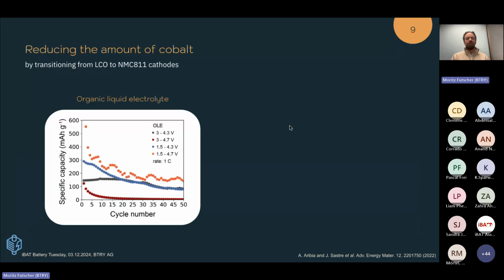So let's look first at the NMC811 cathode. This is work which was developed by Abdesselem Mahmoud Bia, one of the co-founders of the company, now the CTO, who developed processes for NMC811 as a cathode. And as far as I know, we are still the only ones who can fabricate these materials and these cathodes in a thin film form factor. Here you can see the performance of these thin film cathodes in liquid electrolytes. Typically, what you see is that you have the standard voltage range from 3 to 4.3 volts. As soon as you change this either to high voltages, you have very strong degradation, or to low voltages, you also have very strong degradation.